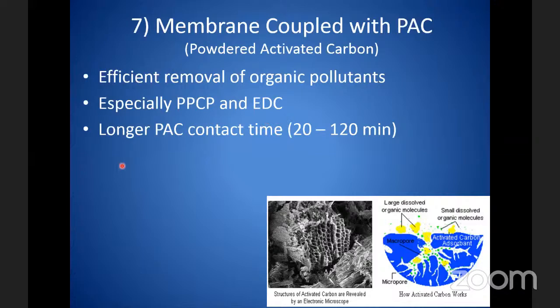So you have longer reaction time. If you put powder activated carbon in the conventional plant, you only have very short detention time or reaction time, because you have to put it before the alum. So you do not have much time before the alum dosing. But if you couple it with the membrane, and your membrane is backwashed every 2 hours, your reaction time goes from 5 or 10 minutes up to 120 minutes. So it's very high reaction time, and it's very efficient for powder activated carbon to react in this way.